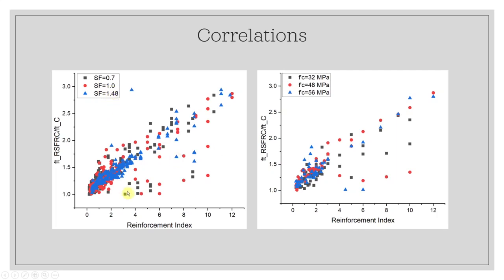So as you see here, this also shows how these results changed to increase the ratio based on the different compressive strength of the concrete. Where you have a 1, it shows that the tensile strength has no significant increase. Almost 1 basically means the tensile strength of recycled steel fiber concrete was equal to the tensile strength of concrete. That basically means no effect, or maybe a very minor effect.